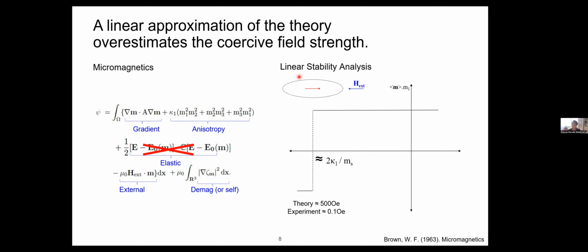And in fact, if you apply this approach of doing a linear approximation of this theory to predict hysteresis for the several nickel iron alloys they tested at Bell Labs, you would predict that the smallest hysteresis or the smallest coercivity would be for the 75% iron nickel alloy composition, and not at 78.5. And so that was also called the Permalloy problem, because it wasn't clear why exactly the 78.5% composition, counterintuitive to the theoretical prediction, is giving you the small coercivity.